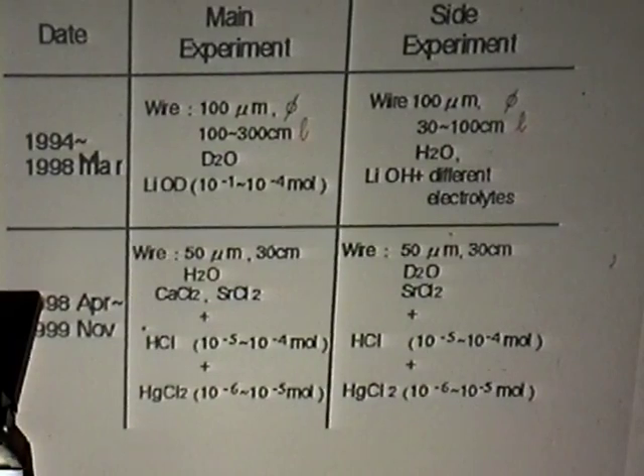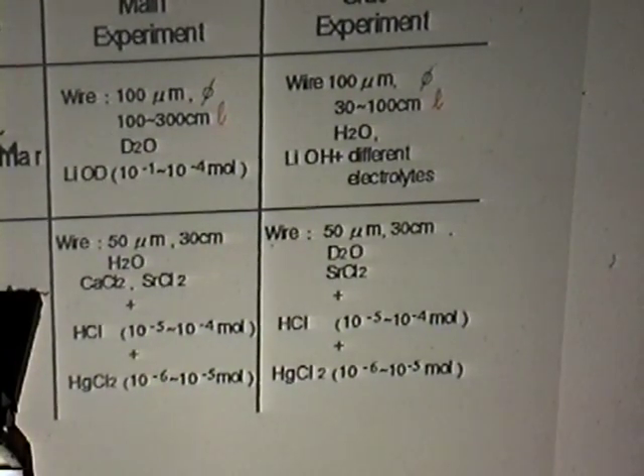It's a small history of our work on using new electrolytes. In '94, we just used 100 micron palladium and lithium. We started to decrease the concentration from 0.1 molar down to 0.1 millimolar. We found some beneficial effect, but not stable. Side experiments used lithium hydroxide, and we tried a lot of different electrolytes. With lithium hydroxide we use light water, so no problem about the money for deuterium. We are free to check everything. Later, we focused our experiments on calcium and strontium, with some addition of mercury chloride. And this approach seems the good one.